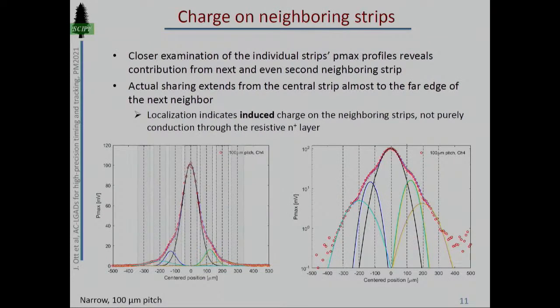So far, so good, but we wanted to look a bit more into the fundamentals of charge sharing. What we see from the amplitude profiles as a function of position is that they're actually not smooth. You can really distinguish here, in the narrow pitch, localized contributions from the neighboring strips.